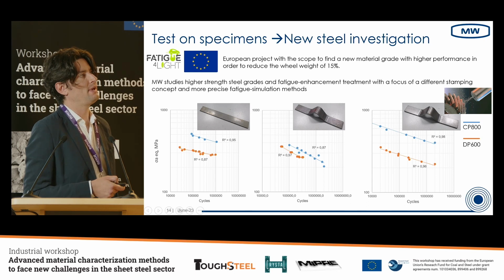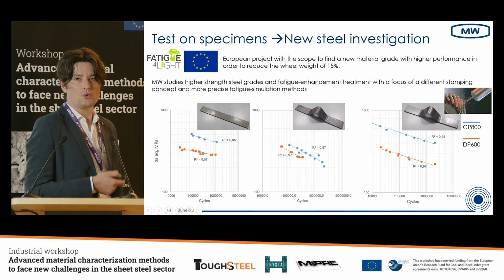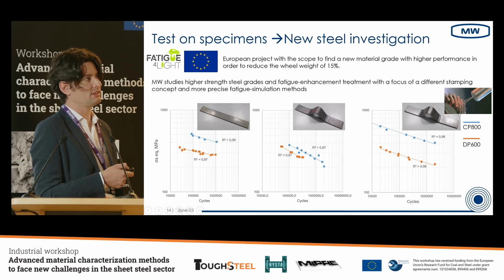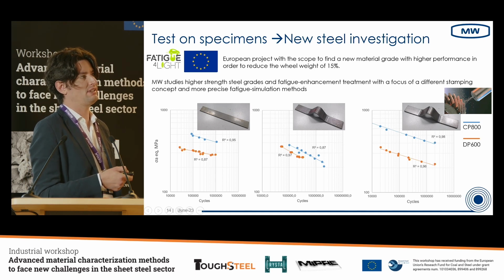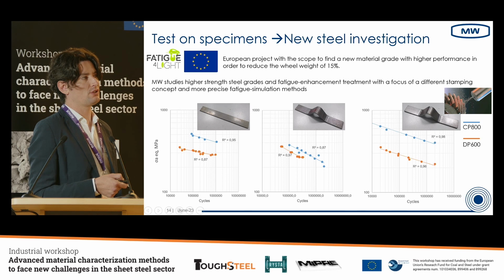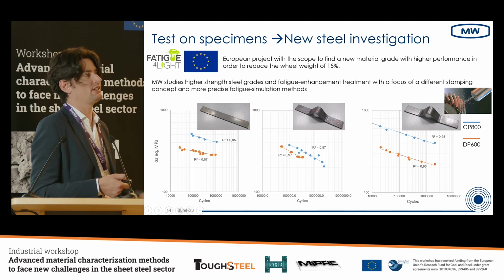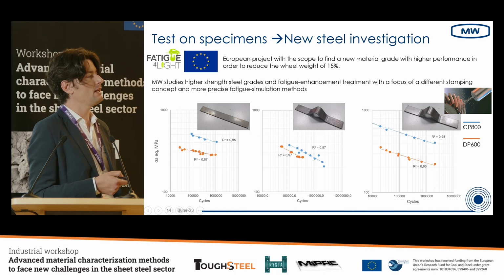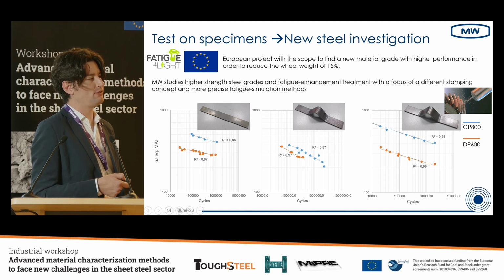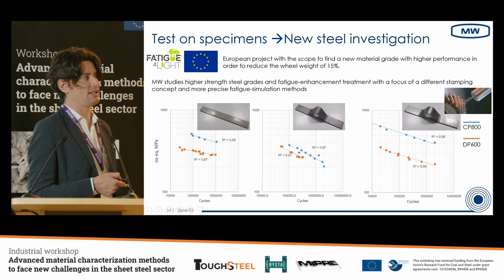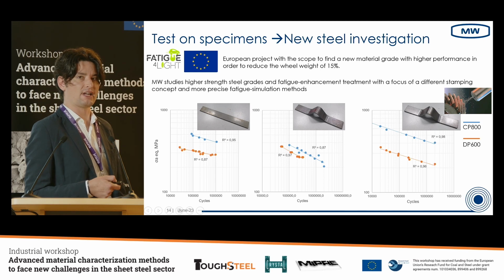Then the test on specimen is the test that we did in the Fatigue for Light project, which has the scope to reduce the weight of the car by 15%. So in that case, we tested a new material. As I said before, the material for the disc usually is DP600. We tried to go to complex phase CP800 with the scope to reduce the thickness and so consequently the weight of the wheel. If we compare the results in a Wöhler graph with a flat specimen, we see that the CP800 is very good compared to DP600. But if we bend, this difference is not so evident.